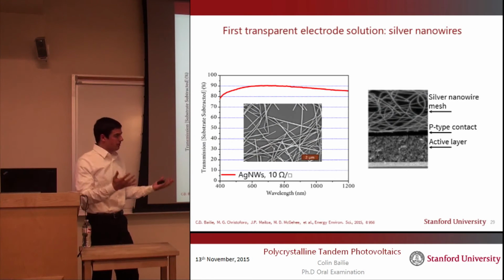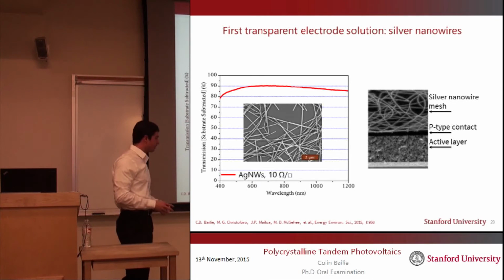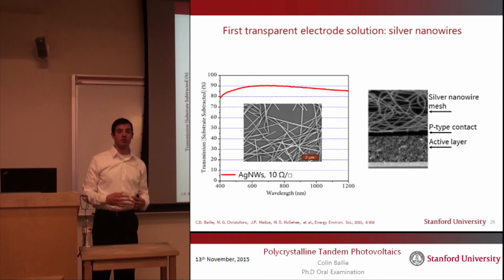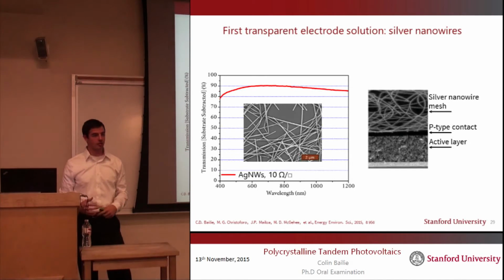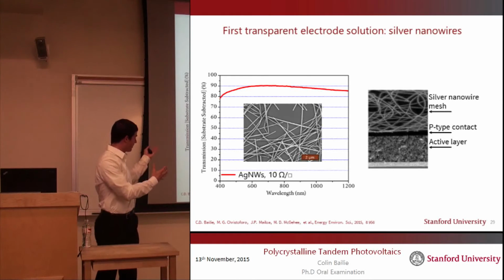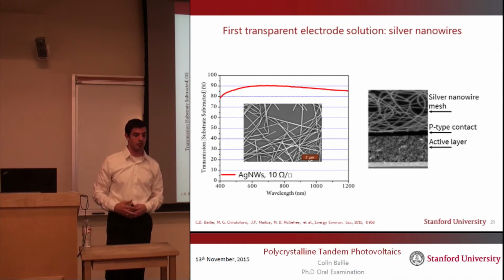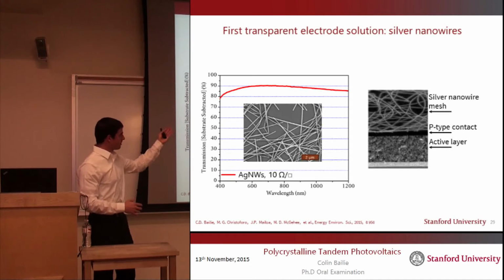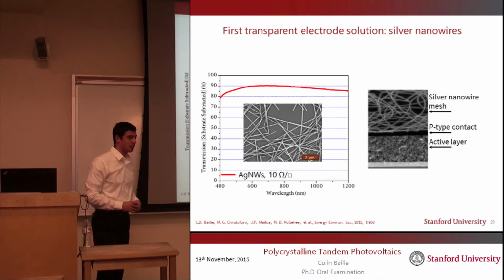And so the initial solution that we came up with for this transparent electrode was to use silver nanowires. And silver nanowires are a transparent, highly conductive electrode. And if you've never seen them before, it sort of looks like you spilled spaghetti on top of your solar cell.